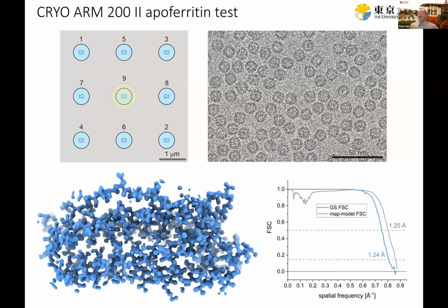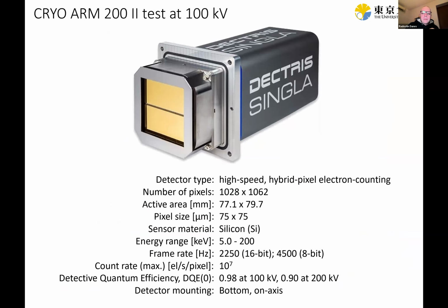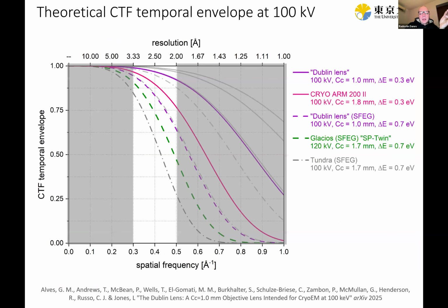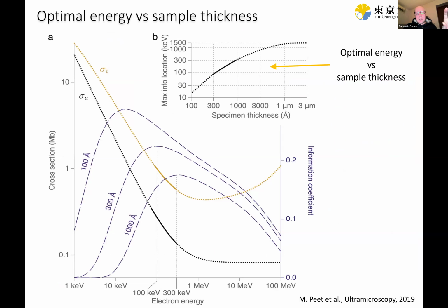Thank you. One question for those who want to do tomography with 200 or 100 kilovolt: what considerations would you recommend? Well, I would say go to a 300 machine. It only makes sense to do tomography if your sample is thin. You saw the plot here. Consider what the tilt angle range would be, and if you do plus minus 60, the sample thickness is doubled at the 60-degree tilt angle. So if you want to collect at 200, you either use a limited tilt range or, yeah, I don't know. It depends on the type of sample.